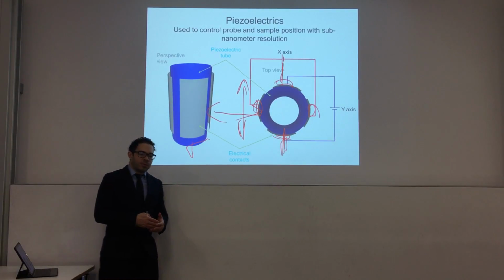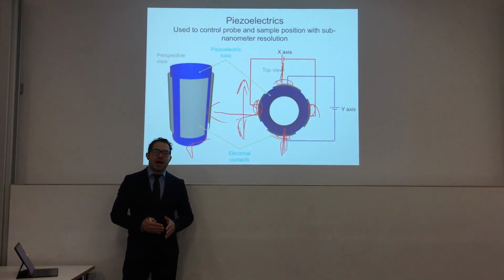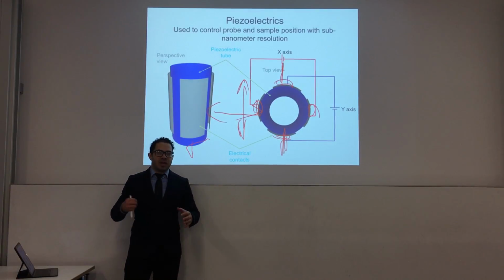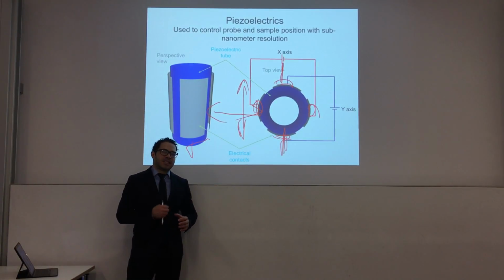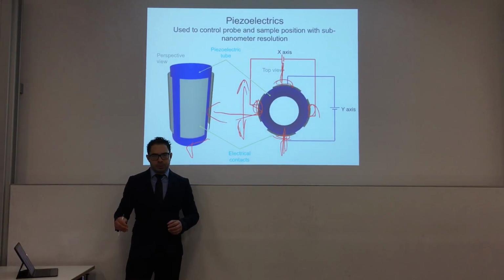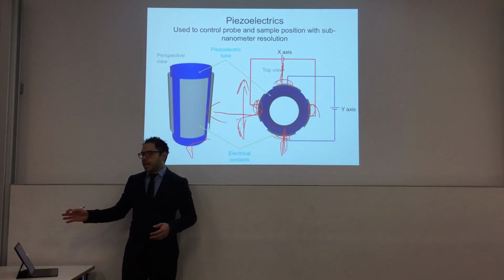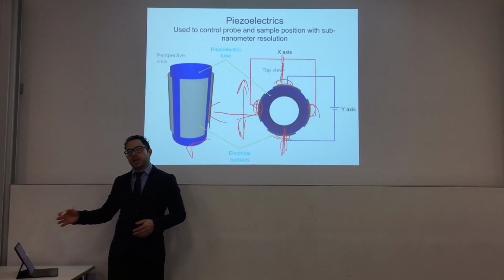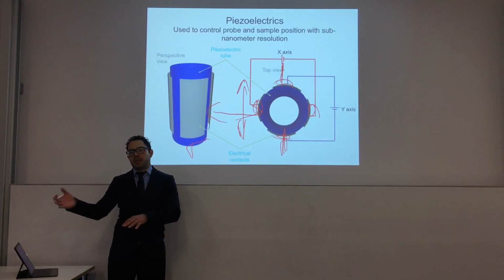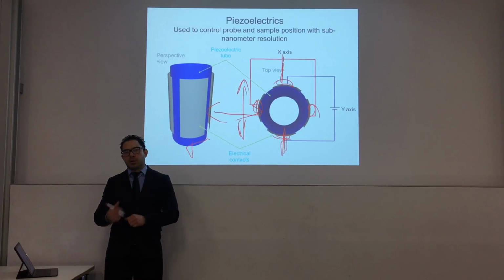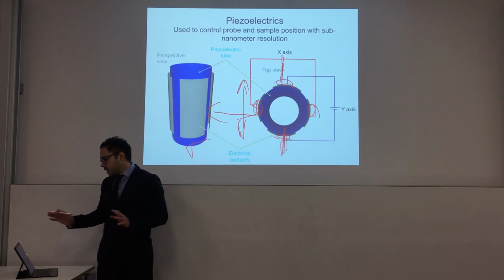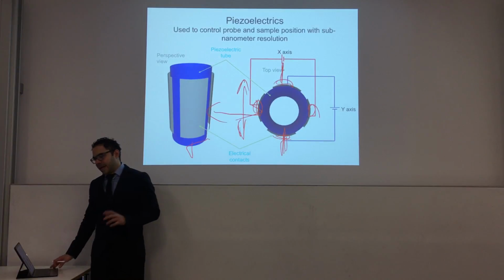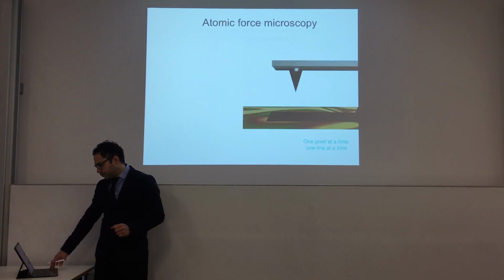And I mentioned to you before, for example, in the case of STM, that you have the current that the system tries to keep constant all the time. So this is your set point parameter using the feedback loop. Now, if the system recognizes that there is a change in current, it will apply a potential to the piezoelectric tube in order to either decrease or increase the tip-sample distance, depending on how the current changes. And this is one of the most important components of any scanning probe microscopy method until now.